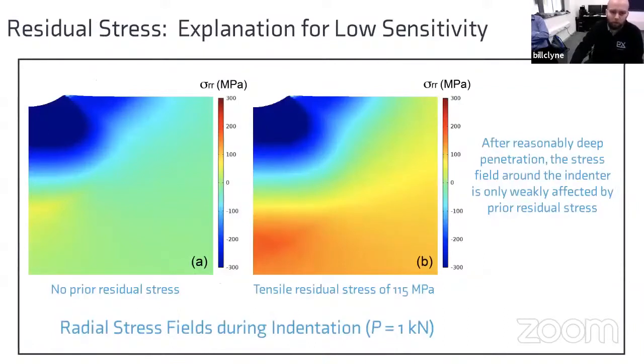So one reason that you can look at to explain this is that after a reasonable penetration, the radial stress fields look quite similar, whether there is no prior residual stress or a tensile residual stress here of 115 megapascals. So you can see that the field is dominated by the plasticity that has occurred. And that may help to explain why we don't see very good sensitivity to the residual stress.